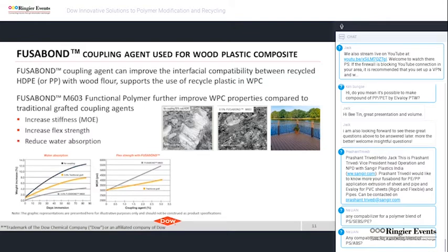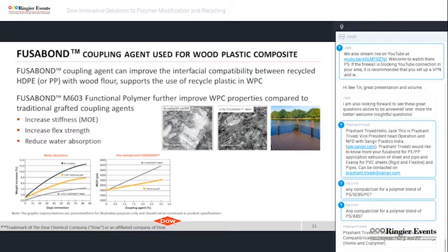Wood plastic composite is compound consisting of a basic resin, typically PE, PP or PVC, reinforced with wood flour. In HDPE or PP wood composite, recycled HDPE or PP is commonly used. Fusabond coupling agent can be used to improve the interfacial compatibility between recycled HDPE or PP with wood flour. When compared to traditional grafted coupling agents, Fusabond M603 functional polymer further improves the stiffness, flex strength, and reduces water absorption of wood plastic composite.